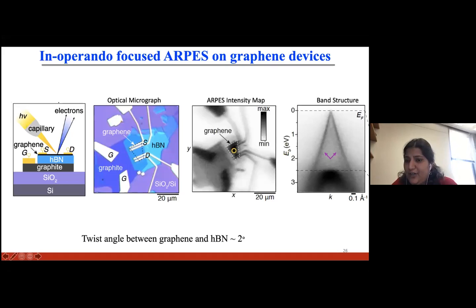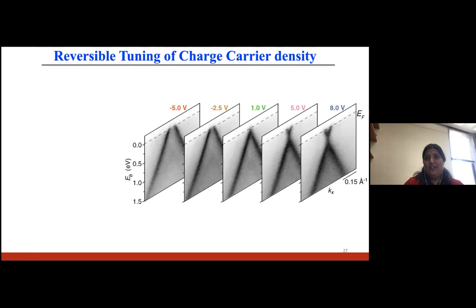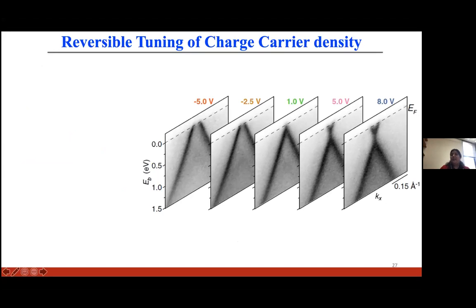If you look carefully, you can also see there are faint bands here, which I'm pointing to with these pink arrows. These are formed due to the mini Brillouin zone of the graphene hBN superlattice, as we had a twist angle of about 2 degrees between our graphene and hBN. Next, let us look at the detailed dispersion of the Dirac cones with gate voltage. By tuning the gate voltage to negative voltage, I can p-dope my sample. By tuning to positive gate voltage, I can n-dope my sample, and I can now get access to the conduction band. If you look at this 8 volt here, you will see that the conduction band and the valence band are no longer touching each other at a point.